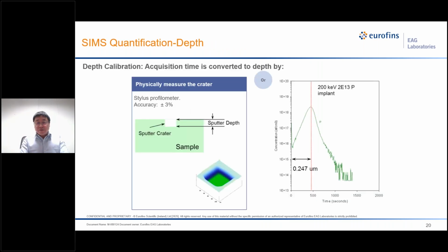So how to quantify the depth? We have two methods. If we know the peak concentration for an implant species, in this case phosphorus, so we know the peak position, and we just put in the peak depth, and then we can convert the time scale into the depth scale. Or we can physically measure the crater after the SIMS measurement, after the profile. Here it shows the profilometer image, and once we measure the crater with the profilometer, then we can convert the time scale to depth scale.